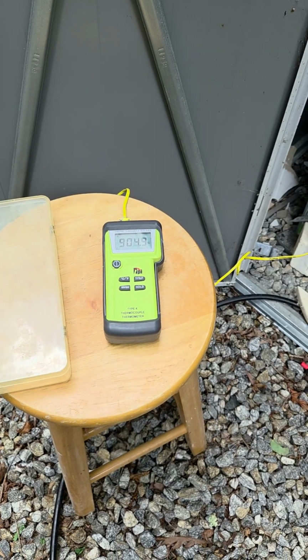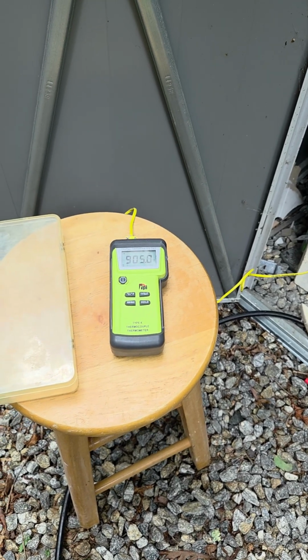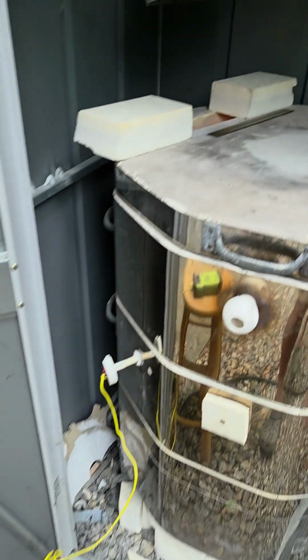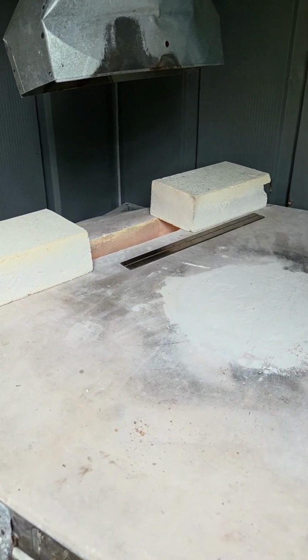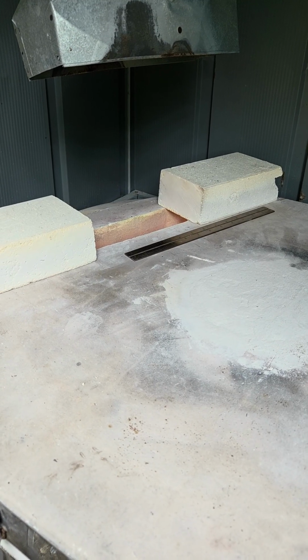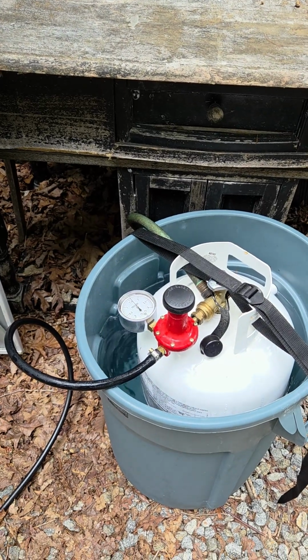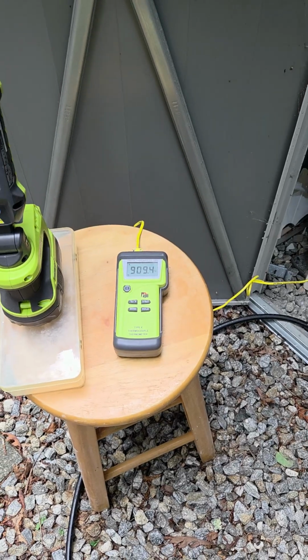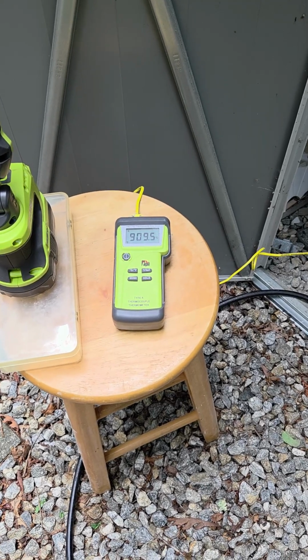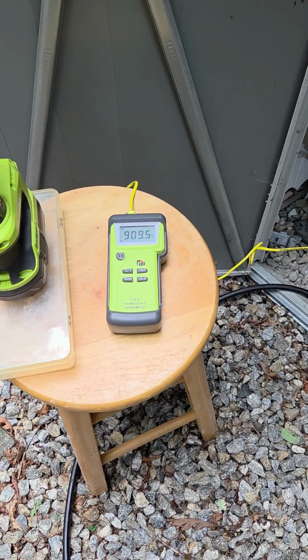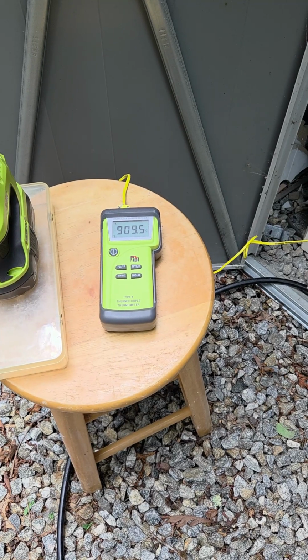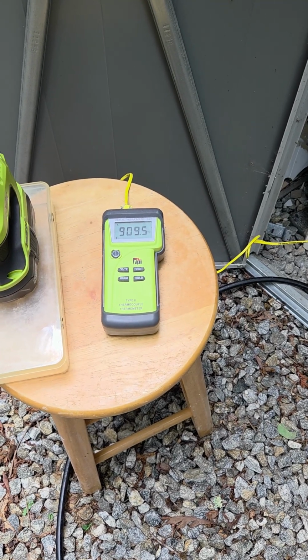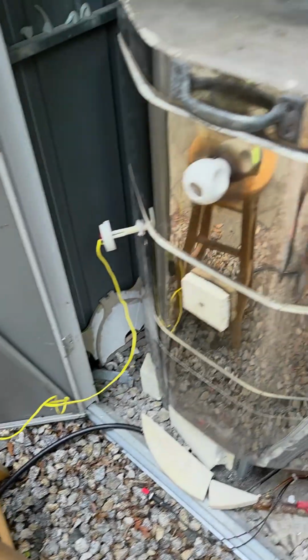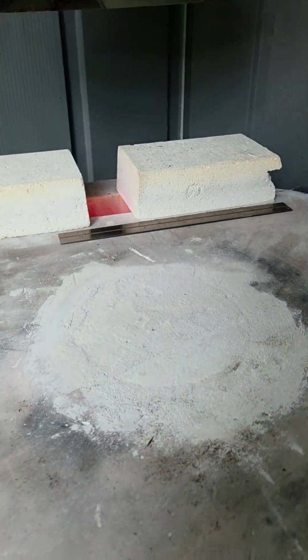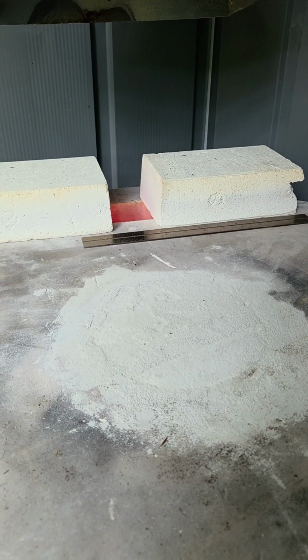So I've gotten up to about 905 degrees centigrade. So the next steps are going to be to choke down the blocks to 2 3/8 inch and then turn up the gas to about 1.9 psi. The kiln was choked off about a minute ago, and it had gotten up to about 909.5 degrees. It's choked down to 2 3/8 inch.